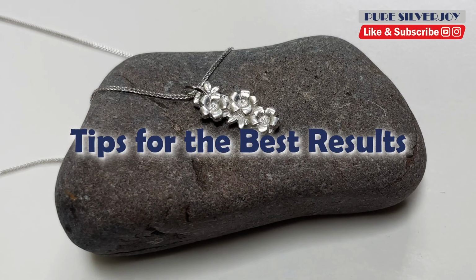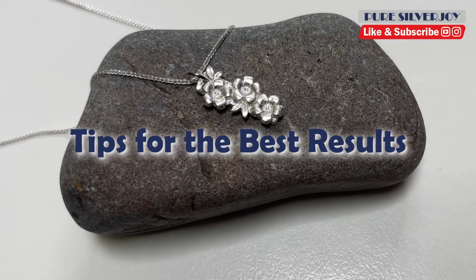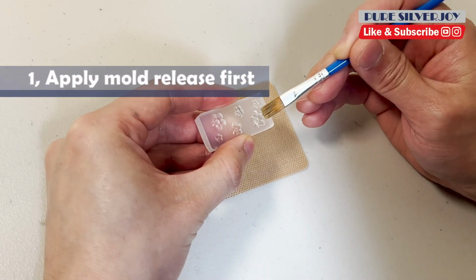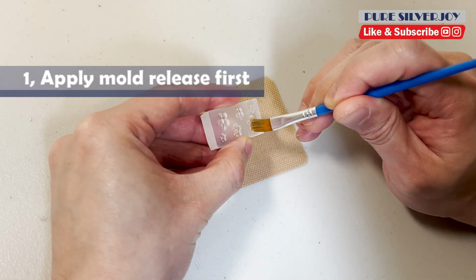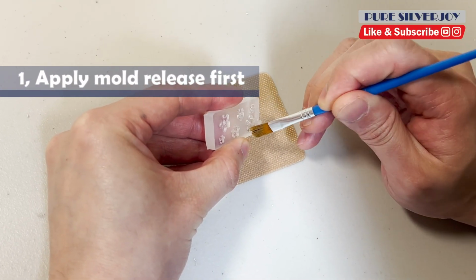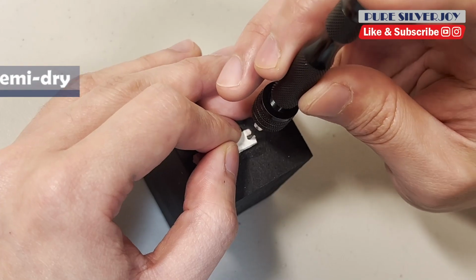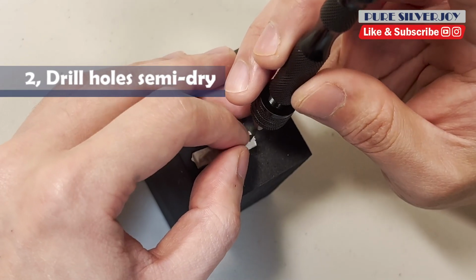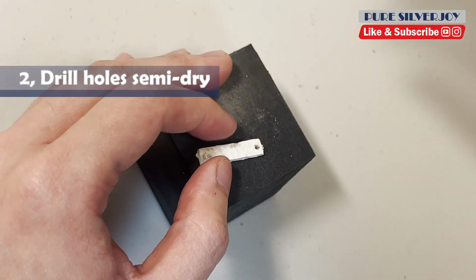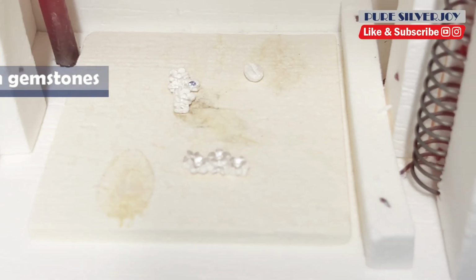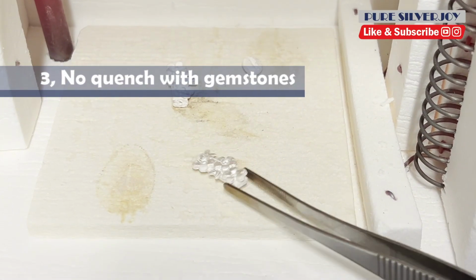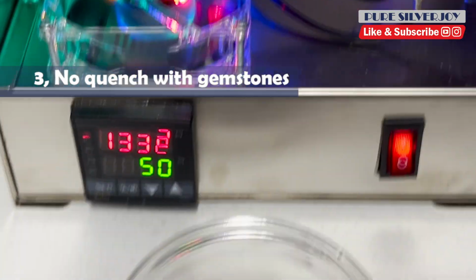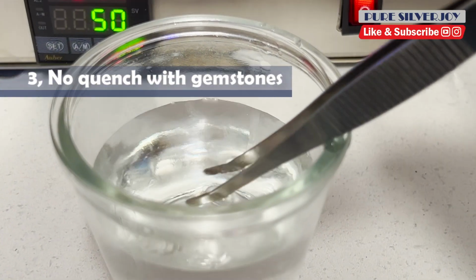Here are some tips to help you achieve better results. First, apply mold release to the mold. It helps remove the silver clay cleanly. Second, make sure to drill holes while the clay is semi-dry. Third, water quenching is only suitable for pieces without gemstones, otherwise, gemstones may crack due to thermal shock.